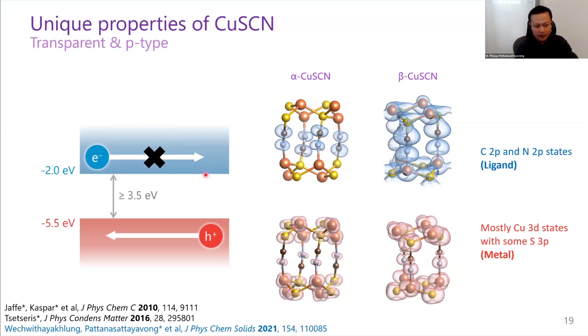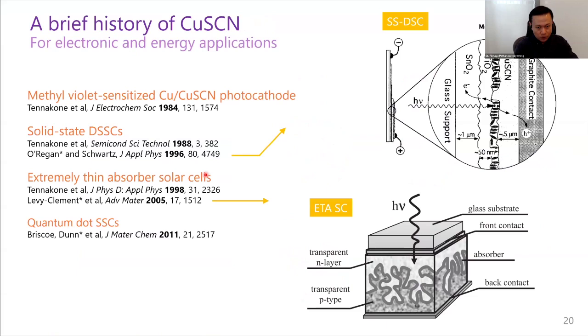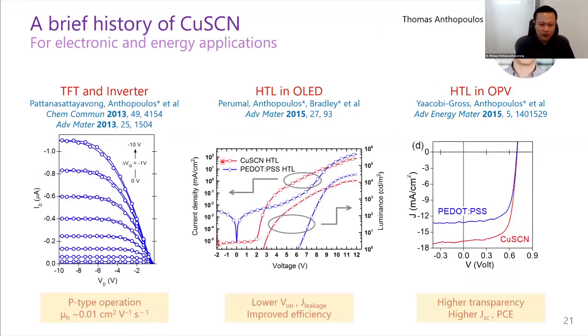And then we looked at this as an alternative material that was first used from the dye sensitized solar cells community by Professor Brian O'Regan. I met him when he was at Imperial College as well. So we learned about this material from Brian O'Regan, that he successfully used it as a solid hole transporter in dye solar cells. And then we tried to apply that as a semiconductor on its own as part of my PhD. So we successfully showed that CuSCN, copper thiocyanate, is a P-type semiconductor on its own, and can be used.